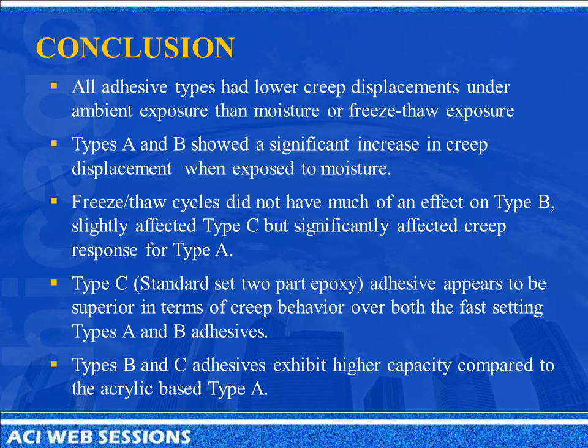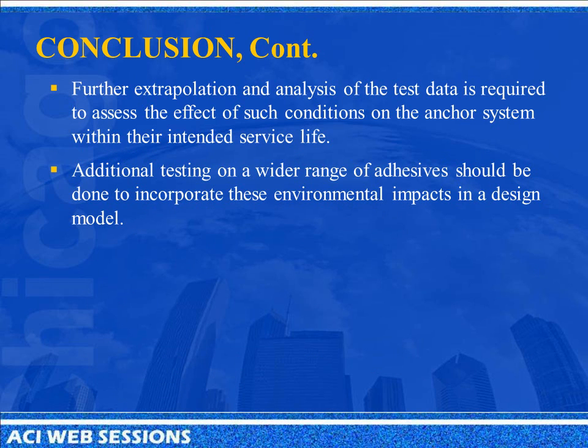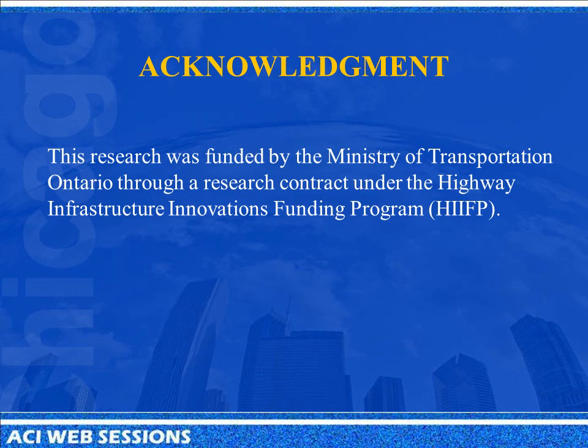Types B and C, the epoxy-based ones, again in terms of static pullout capacities, exhibit a higher capacity compared to the acrylic-based one, type A. Further extrapolation and analysis of the test data is required to assess the effect of such conditions on the anchoring system. Additional testing on a wider range of adhesives should be done to incorporate these environmental impacts in a design model. Finally, I would like to acknowledge the Ministry of Transportation of Ontario for funding this research, and thank you.